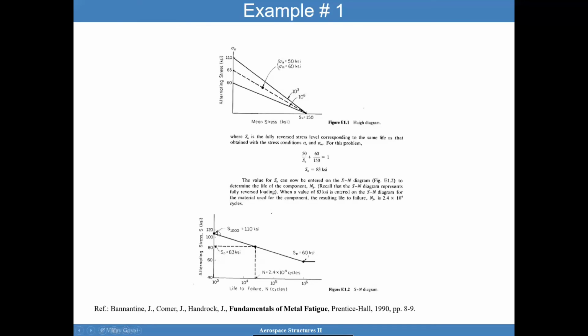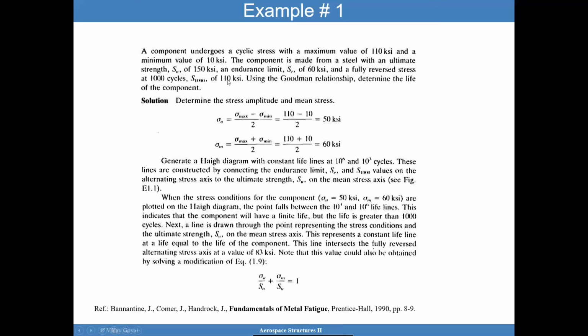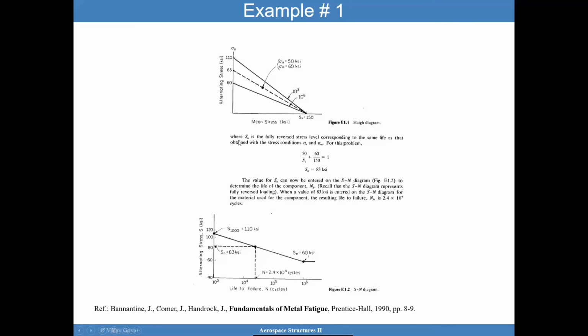Now go to your SN diagram. The SN diagram at 1,000 cycles is 110 KSI. They tell you that per testing. And then here at 60 KSI is your endurance limit. And that's usually at 1,000,000 cycles. So you can draw this line very readily. Go here, say, okay, I have 83 KSI. And then this tells me that I'll have 2.4 10 to the fourth number of cycles. So that's the solution to this problem.